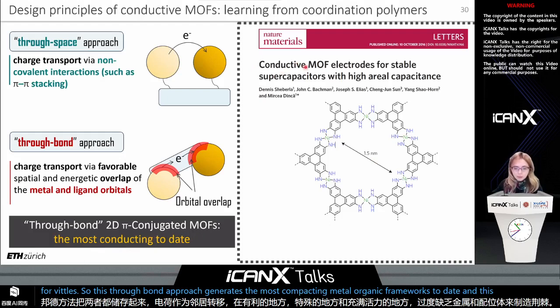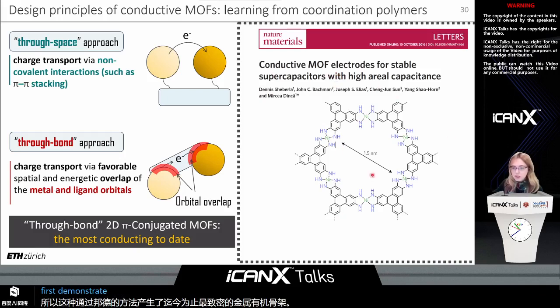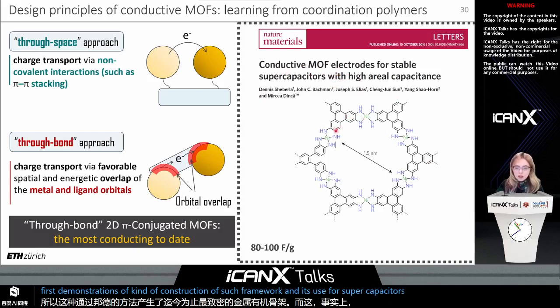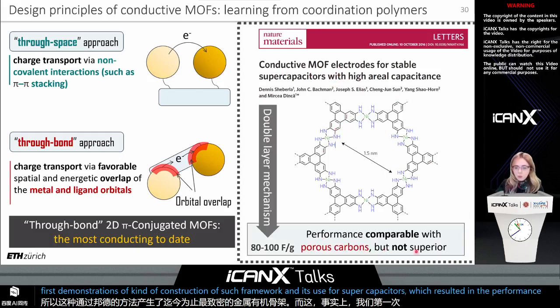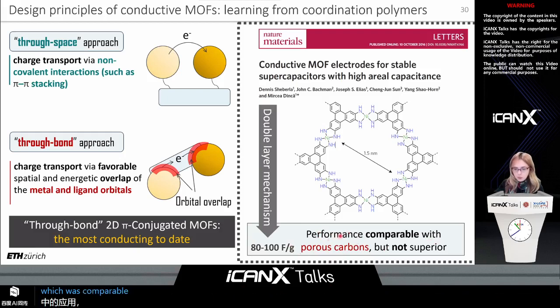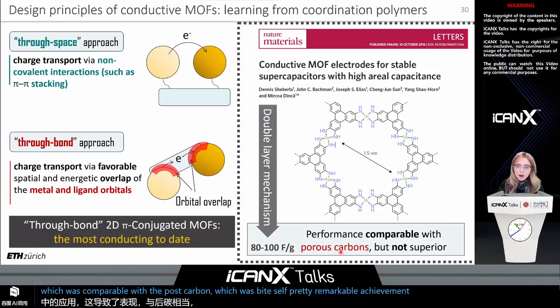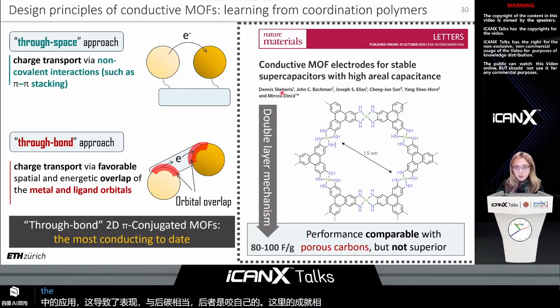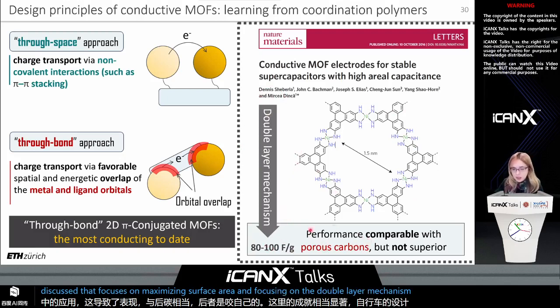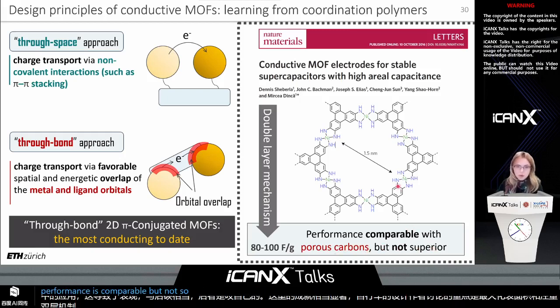This, in fact, was the first demonstration of the construction of such a framework and its use for supercapacitors, which resulted in performance comparable with porous carbon, which was by itself a pretty remarkable achievement. Here, by design, the authors discuss that the focus is on maximizing surface area and the double layer mechanism. So it's unsurprising that the performance is comparable, but not superior to porous carbons.